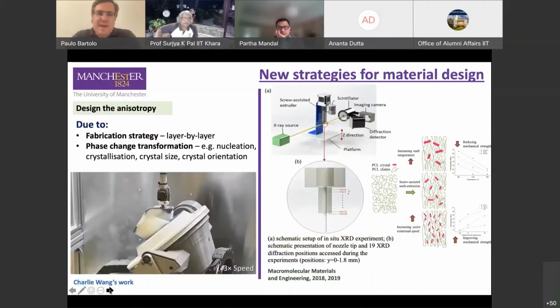But additive manufacturing also has some limitations that we need to consider when we design a part, and this does not depend on the materials. I'm going to focus more on polymers, of course. And one of the key problems is related to the anisotropy. Anisotropy in additive manufacturing is due to the fabrication strategy, because we are producing parts layer by layer, but it's also due to the phase change transformation that the material suffers during the printing process.